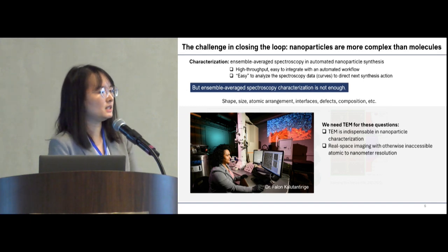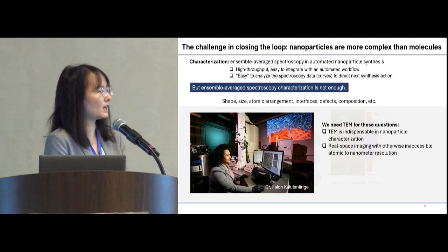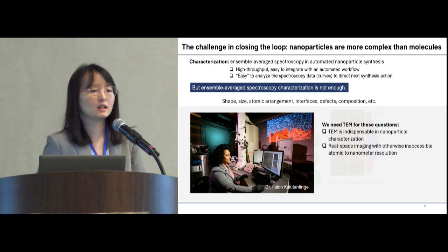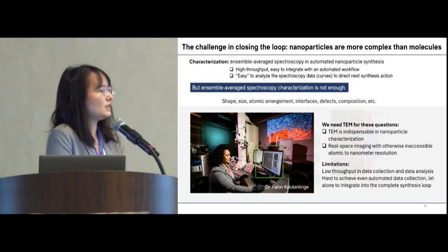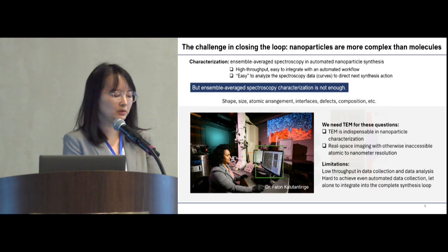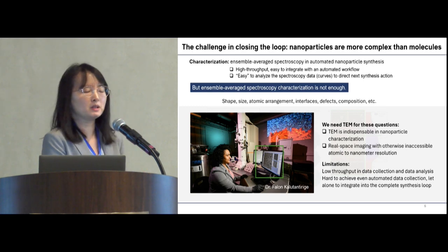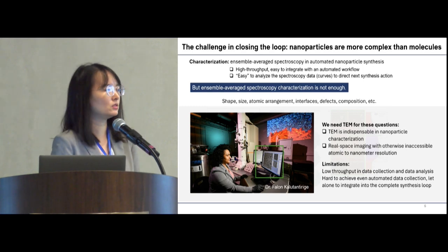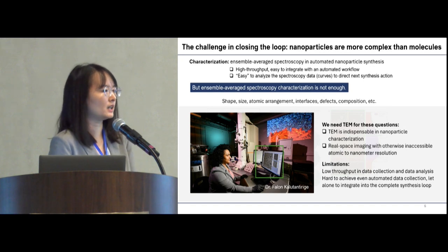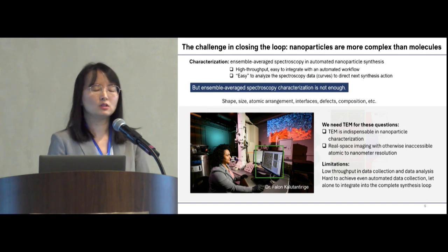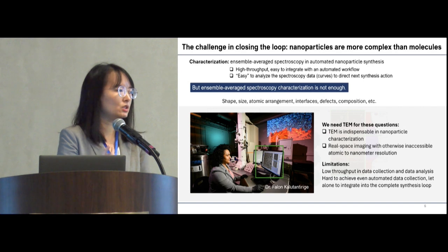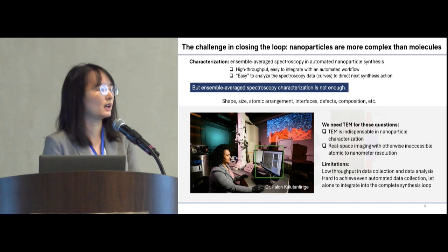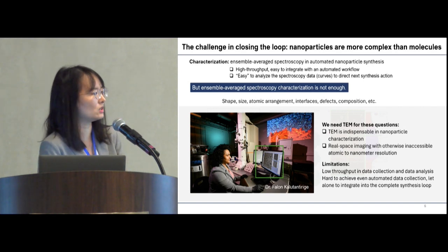But the reason why TEM has not been included in those automated materials discovery platforms is because it has limitations. So TEM is notoriously low throughput. In this photo, my former PhD student, Phonon, basically had to sit in the dark room of the electron microscope for hours to manually select regions of interest, to manually do the alignment of the microscope to collect images.